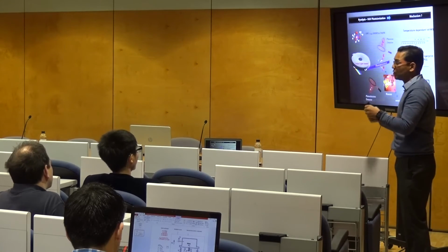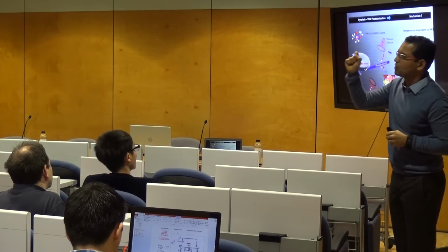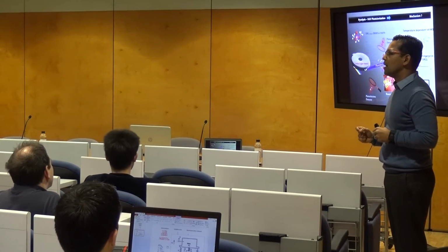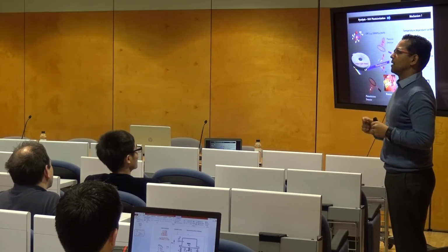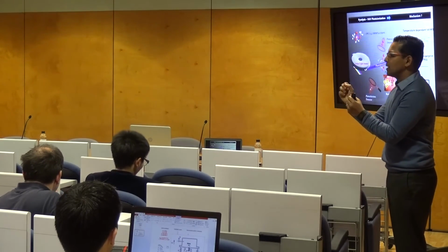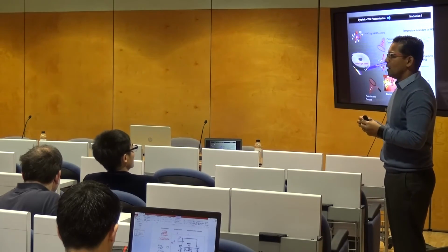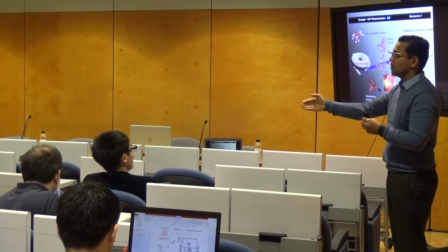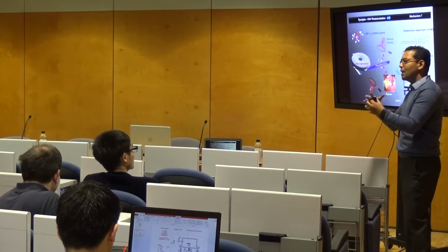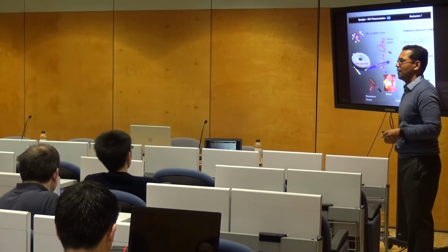And that's the key, because we really want to know exactly, we need to freeze the molecules or the species which are formed right when it is decomposing. Sometimes the rate of the splitting apart is very, very high. It takes, I don't know, a fraction of a millisecond. You might have some secondary reactions, which we cannot avoid. But when we make a molecular beam, we are able to see most of the species. Really a lot of these species.